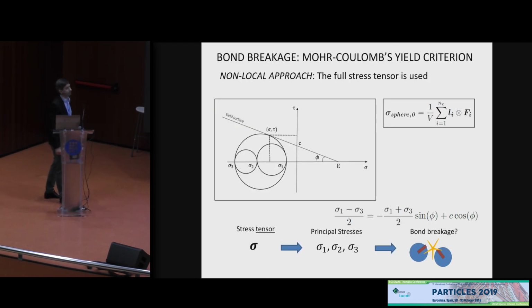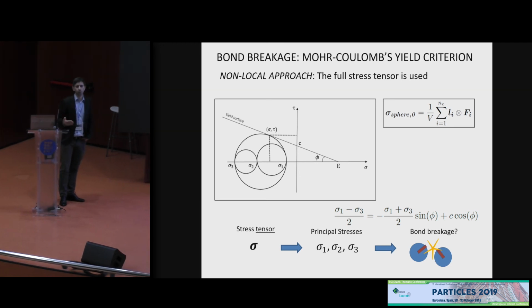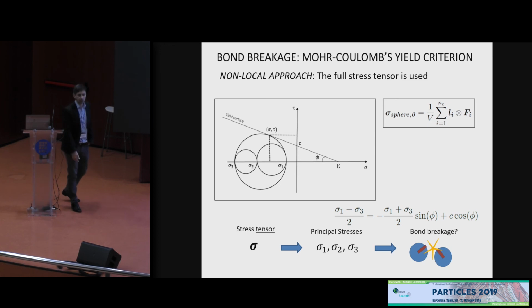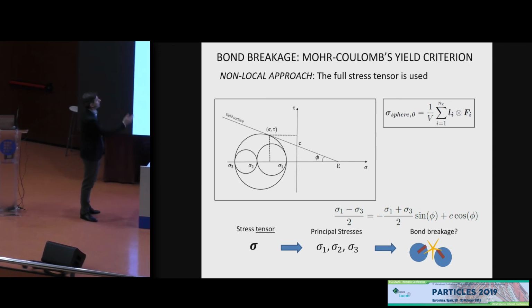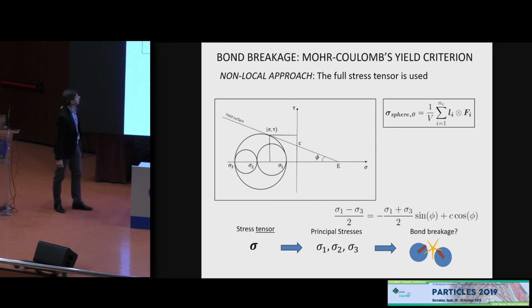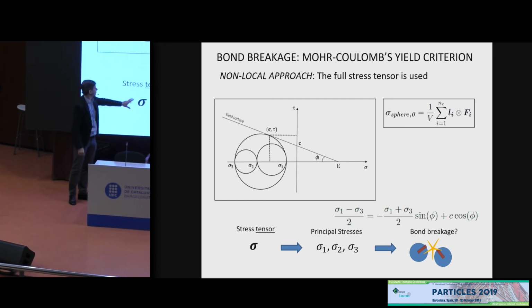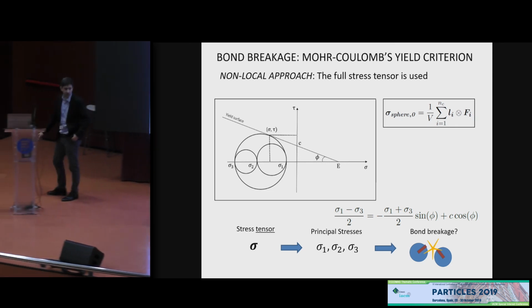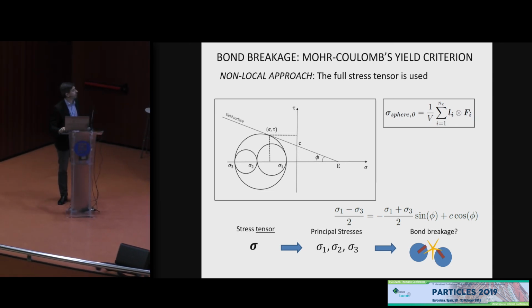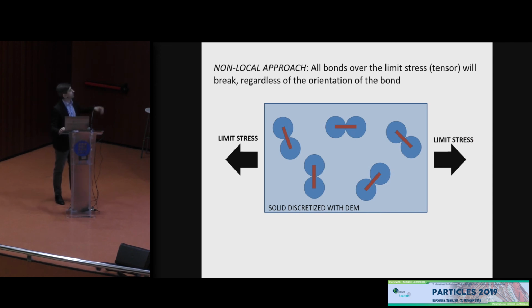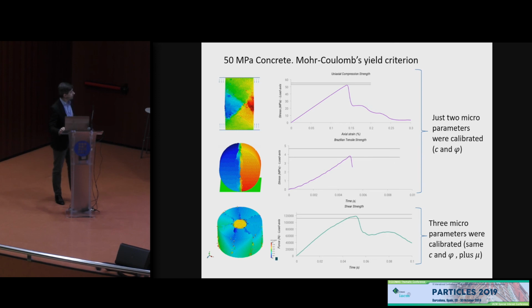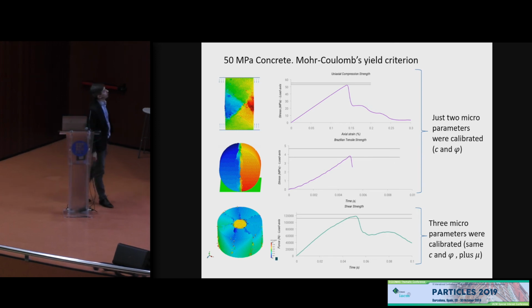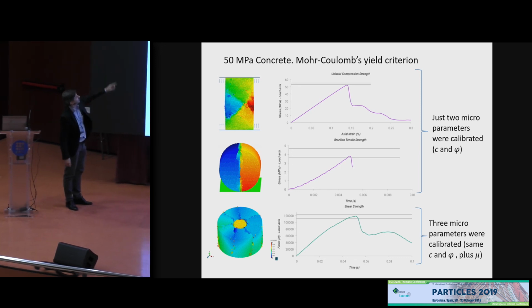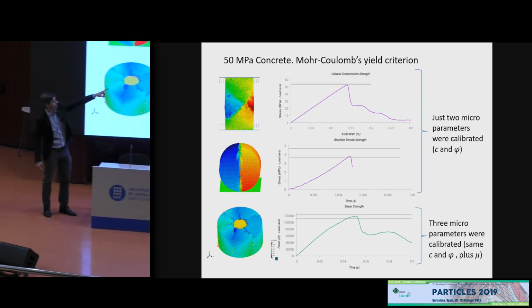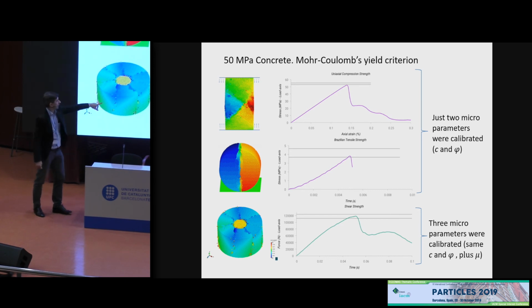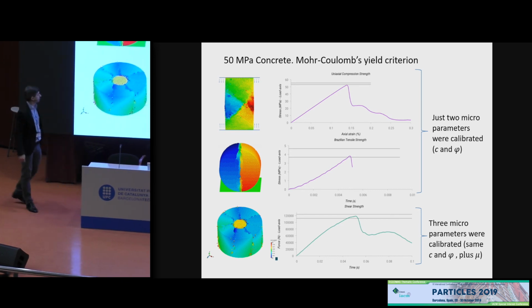But we said, okay, if we can do this with a Rankine yield surface, why not Mohr-Coulomb, Drucker-Prager, Tresca, von Mises, whatever you have used traditionally? Well, we tried Mohr-Coulomb, and the concept is the same. You have this yield surface, you have the stress tensor at the point, you take the principal stresses, you can operate with them and assess if the bond is breaking. Then the same thing. Bonds are breaking regardless of the orientation, and those are the results comparing with experiments for the same 3 tests. But here we had to calibrate 2 parameters, C and phi, for Mohr-Coulomb, and a third one for the friction in this case.